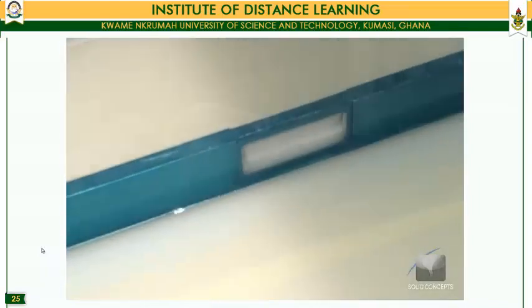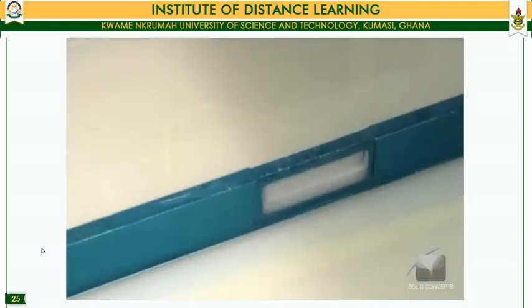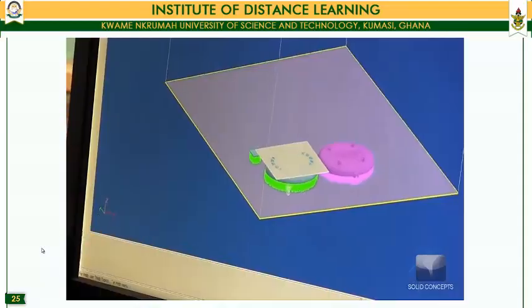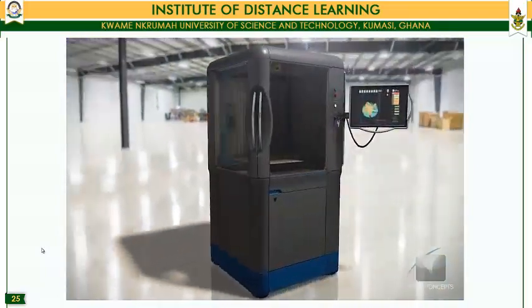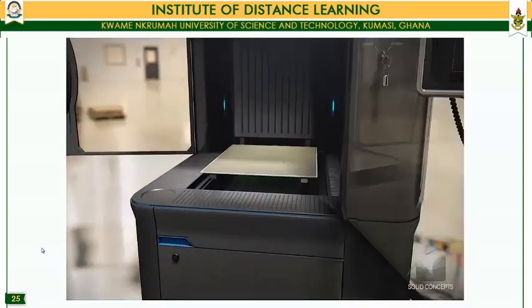Stereolithography is a rapid prototyping process used to create parts from 3D CAD data in a matter of hours. SLA is a highly accurate additive manufacturing process and may also be referred to as rapid prototyping or 3D printing. Models created with this technology are typically used as concept models for form and fit studies or as master patterns for molding techniques. The SLA process begins when CAD data is sliced into thin cross-sections or layers, typically about 6/1000 of an inch thick. This data is then transferred to an SLA additive manufacturing system containing a vat of UV durable photopolymer.